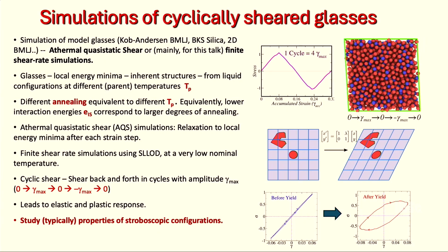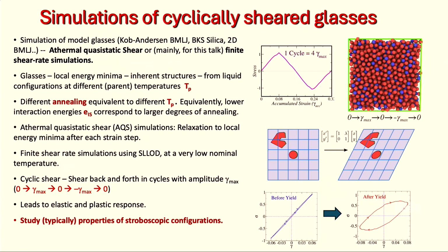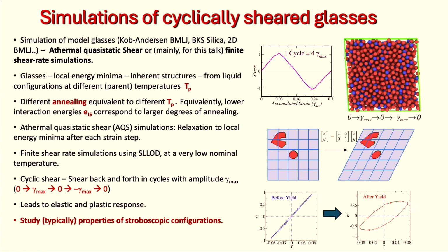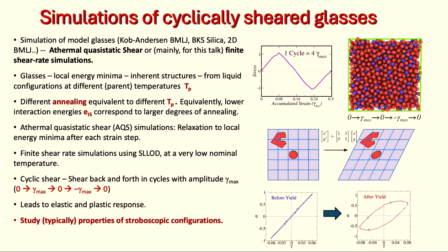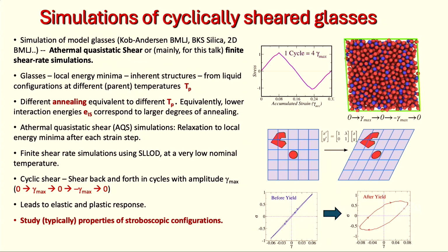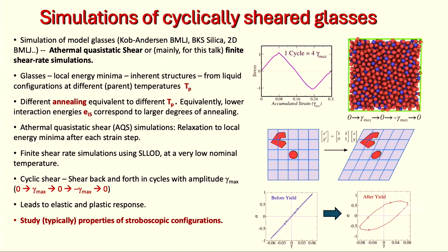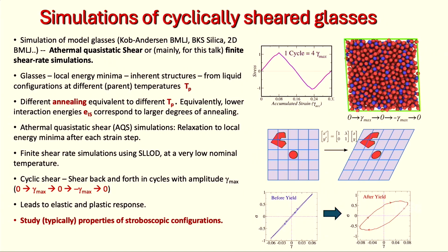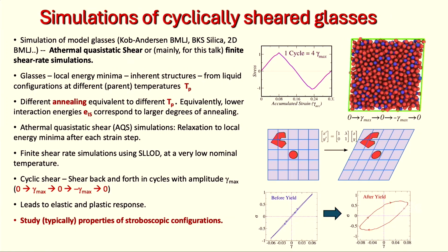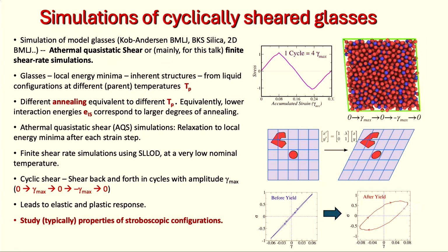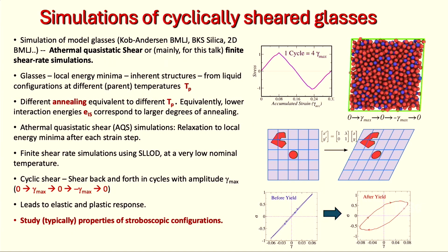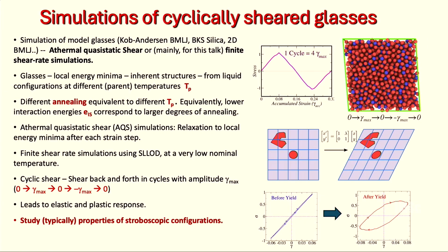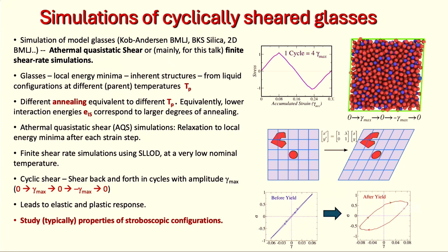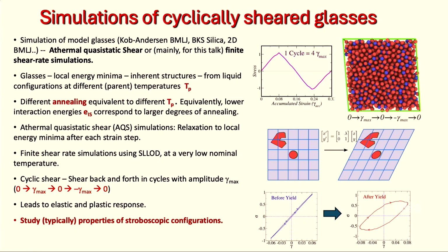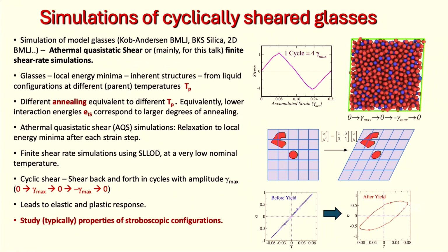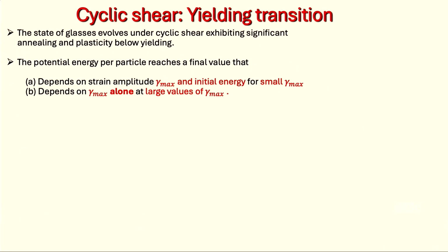And then such glasses are subjected to either what's called athermal quasi-static shear, with no temperatures involved, or finite temperature, finite shear rate simulations. And in each case, we typically look at the properties of the system at the end of each cycle. And because there are plastic rearrangements, the properties of the system change from one cycle to the next, till some steady state is reached.